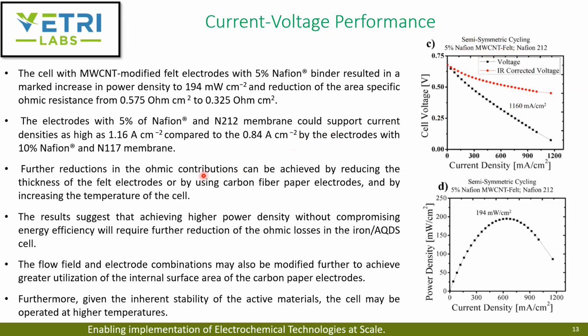Their attribution is that you can still reduce this ohmic contribution by reducing the thickness of the electrodes, which is about 2 to 3 mm, by using carbon fiber paper electrodes that are about microns in thickness, or you can increase the temperature of the cell. These results suggest that you can achieve a higher power density without compromising the energy efficiency. So it will require further reduction of the ohmic losses in the Iron-AQDS flow battery. You can also play around with the flow field or the electrode combinations to achieve greater utilization of the internal surface area of the carbon paper electrodes.